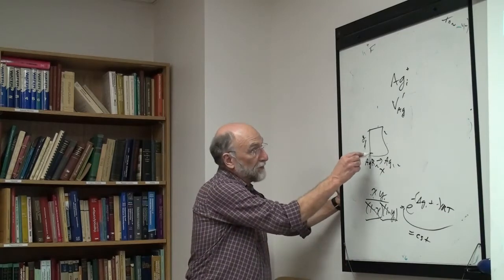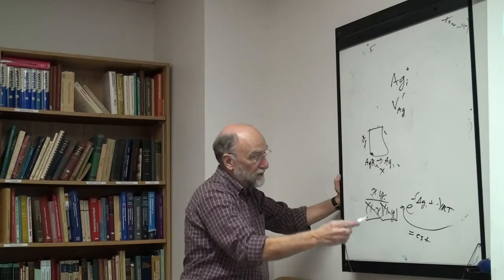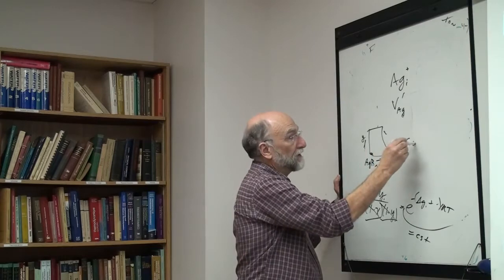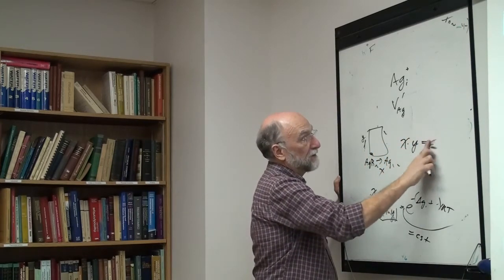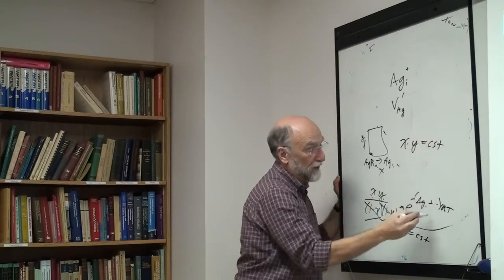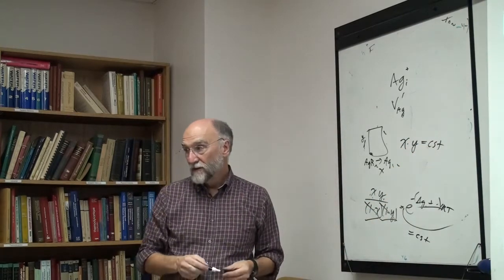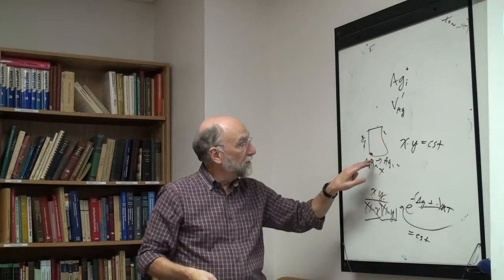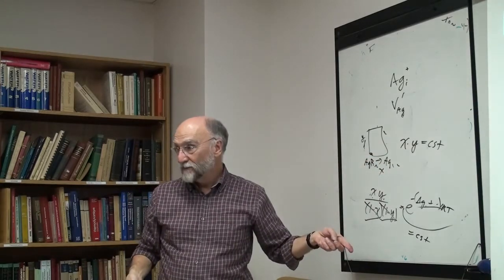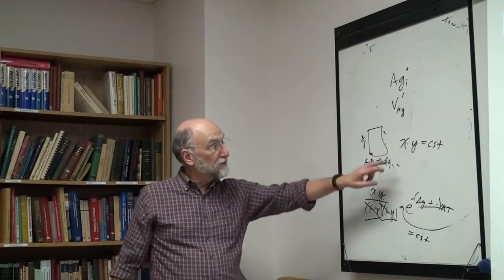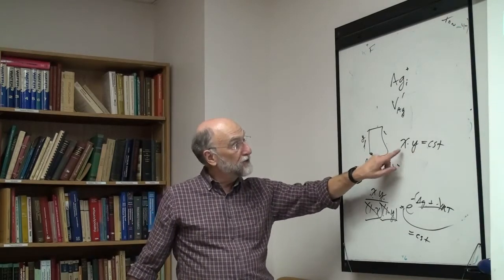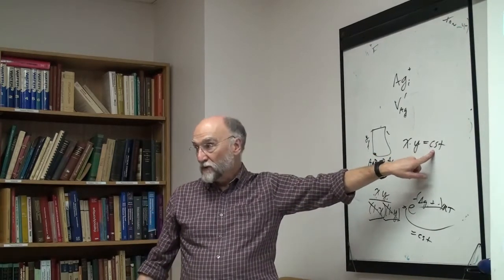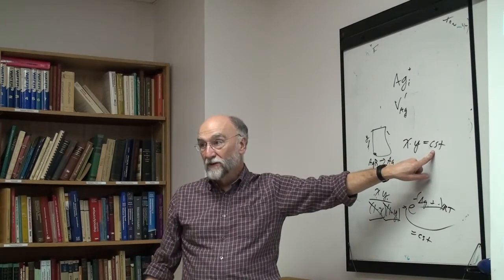So basically, if you're in dilute solution, all of these things end up very simple: the product of the concentrations of the two defects is a constant, which depends upon the energy of forming the defect. This might be x squared y if there's two spaces or something like that. So all of these things reduce down to the simplest equation, that the product of the concentrations of the two majority defects is approximately constant to a first approximation.